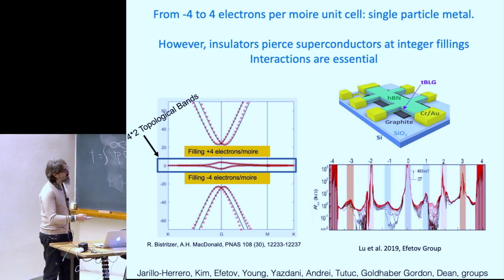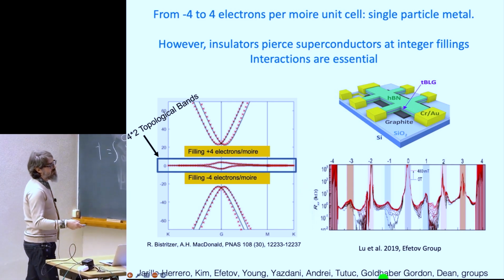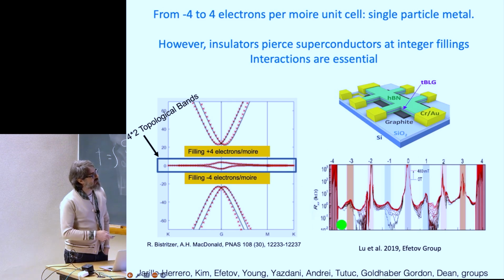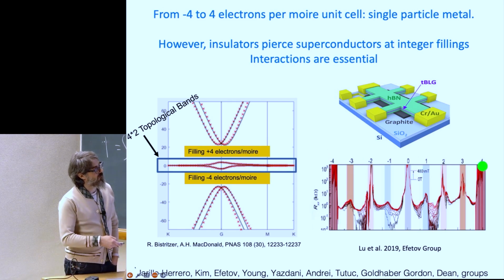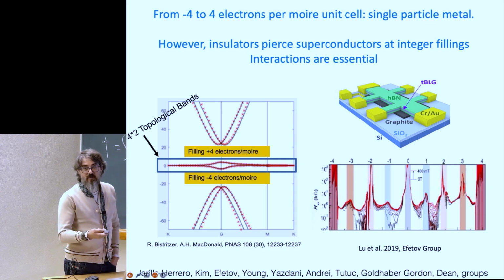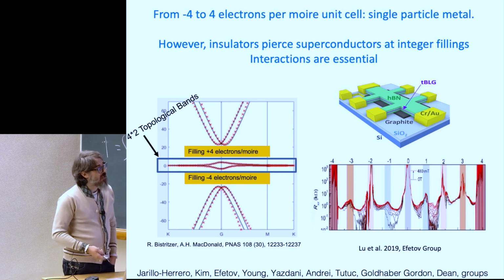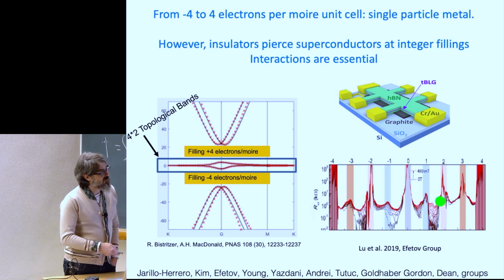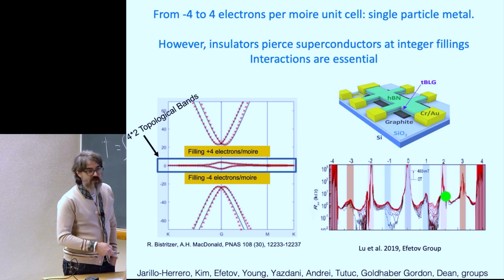But look what happens, and this is data from Dmitri Efetov's group, look what happens in reality. What happens in reality is that as you change the filling from minus 4 to 0 to 4, at integer, so at minus 4 and 4, I have single particle gaps, meaning regions of no electronic states. But in between, in single particle, I should have a metal. Now, you can see the resistivity. This is the resistivity shooting up at integer fillings. For example, minus 2, 2, it shoots up. So resistivity shooting up, highly resistive, means it becomes an insulator. You can moreover see resistivity going to 0 in between these, right? So when I'm at integer filling, I have insulators. When I'm in between them, resistivity goes to 0.